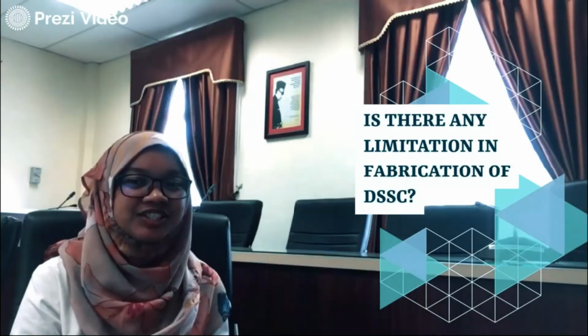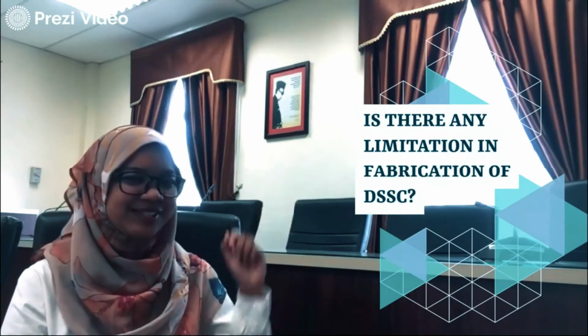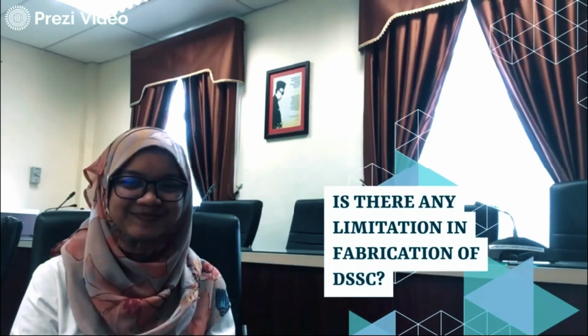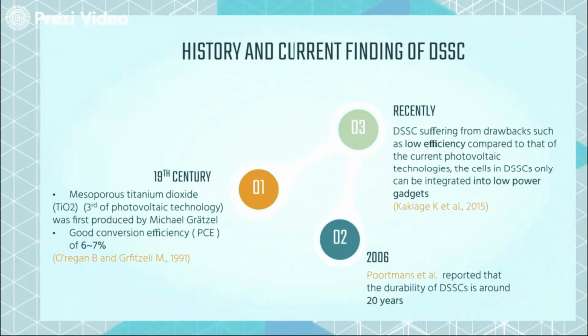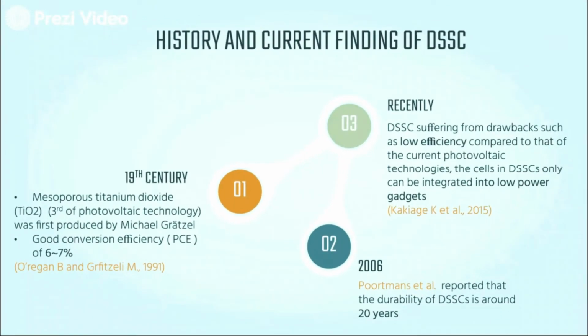Is there any limitation in the fabrication of DSSC? So we have an answer after this. In the 19th century, mesoporous titanium dioxide or TiO2 was actually the third generation of photovoltaic technology founded by Michael Gratzel, and it's found that the good conversion efficiency can go up to 6 to 7%. And in 2006, Poortmans et al. actually reported that the durability of this DSSC is around 20 years. Wow, it's quite a long period.